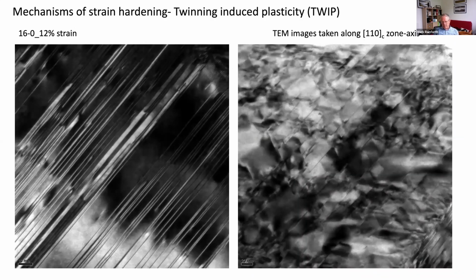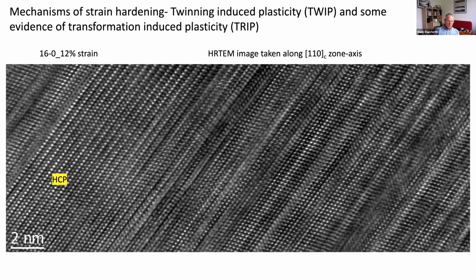Just to show you some beautiful images, this is the TWIP, or twinning induced plasticity, that is taking place during deformation. You can see these beautiful twins. And when you go to high resolution imaging, you can indeed see that there is some transformation to hexagonal phase there as well. So we get both a TRIP and a TWIP effect, and that is what is responsible for getting this very high ductility.